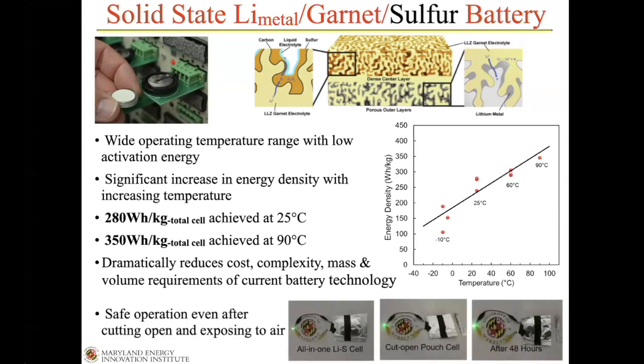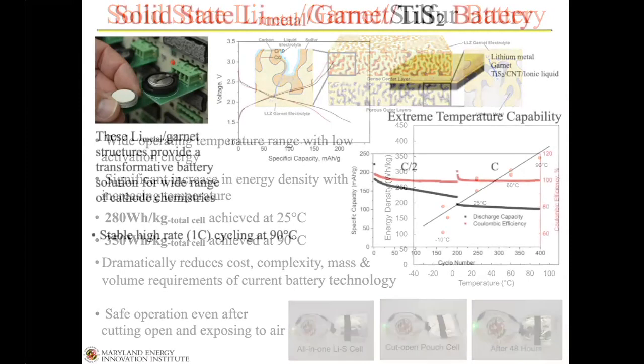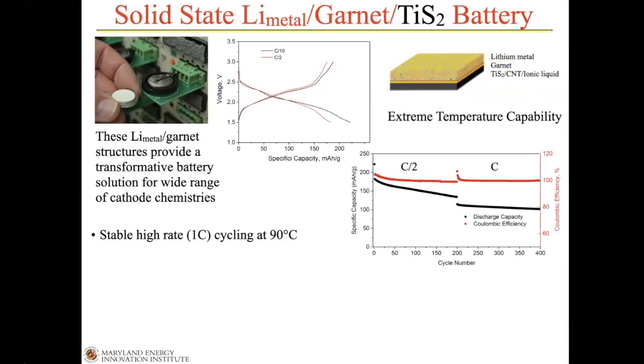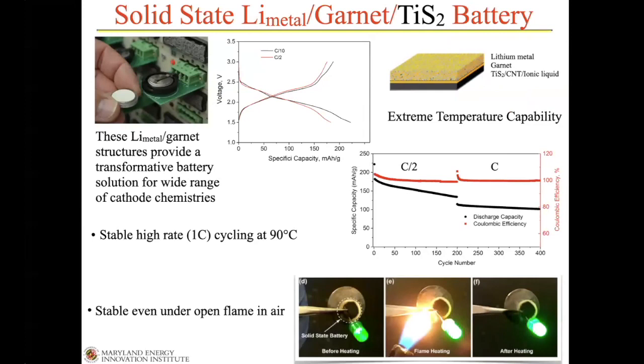The other aspect of that is the safety. Again, these are non-flammable, but now you're seeing the ability to just cut these things open and there's no degradation. They continue to perform without any problem. We've also done this with titanium sulfide, which allows even higher temperature. And now you're seeing 1C cycling at 90 degrees C without any problem. And in fact, talk about safety. This is that titanium sulfide cell under an open flame, absolutely safe. No flame, and in fact, it just shows a higher energy density because the LED lights up farther.